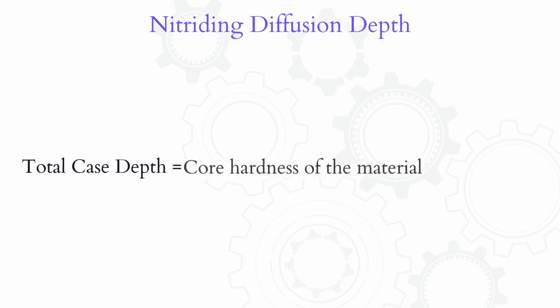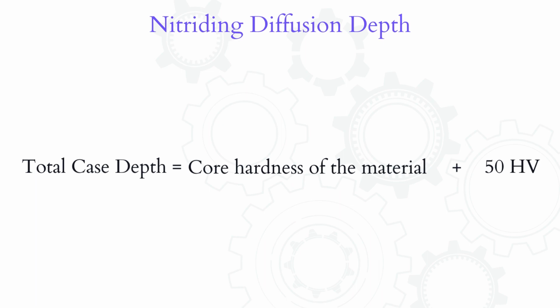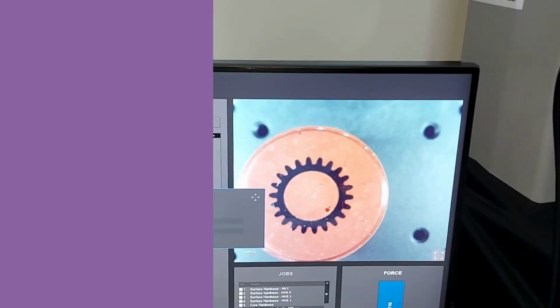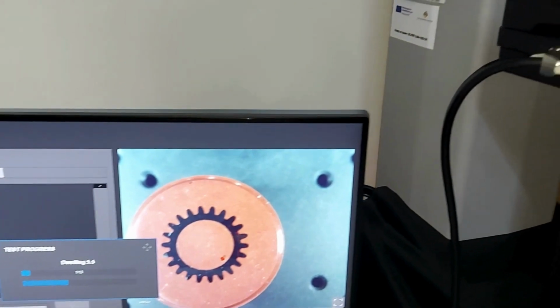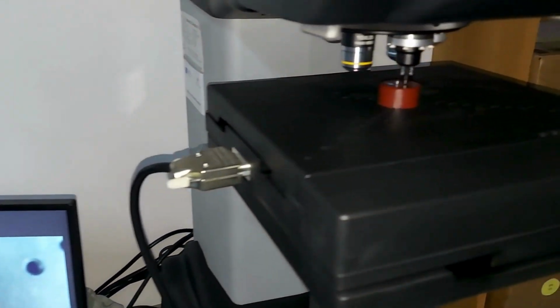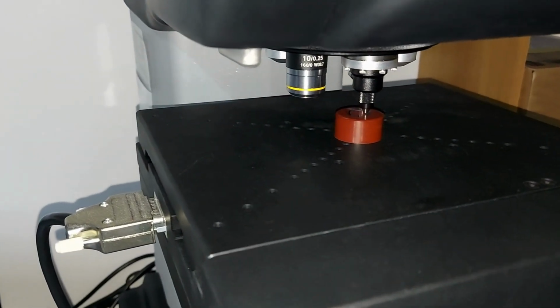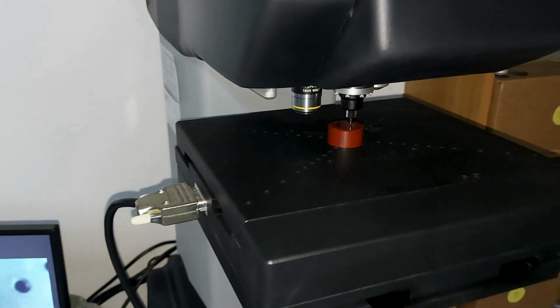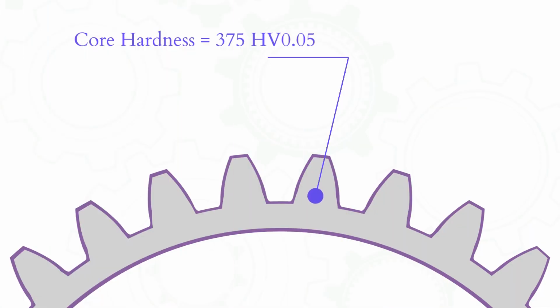Total case depth is measured at 50 HV on top of the core hardness. So first we need to determine the core hardness. We make a few measurements at the core, which is done roughly at center of the cross-section. Again, we make a few measurements with 50 grams and we get the average, which in our case is about 375 HV.